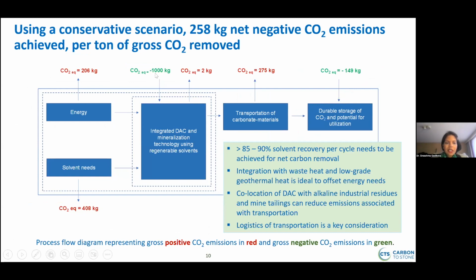In terms of looking at both the positive CO2 emissions as well as the net negative CO2 emissions, we ran a very conservative case with a slag material that is not as reactive compared to the slag that I'd shown you earlier, but is more representative of the general classes of slags. And what we found was that on a net basis, we are able to remove more than 250 kilograms of CO2 per ton of gross CO2 emission. Again, this is a very conservative scenario. I would call this the lower bound. And there are ways to actually increase the carbon removal efficiency.